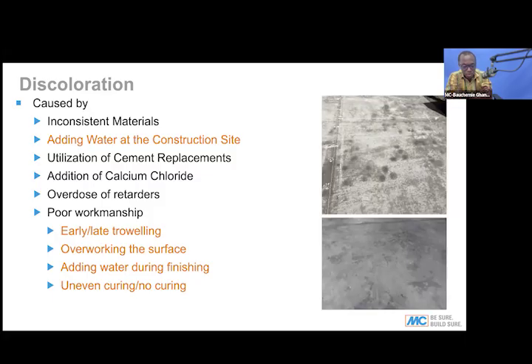Another aspect is when you are constructing, then you add so much water to the concrete. At the plastic stage, when the concrete is drying, you have water on the surface. When the concrete is drying, there will be moisture loss. The moisture loss will leave a lot of cement laitance on the surfaces. And on some of the concrete, when we are finishing, like the tool finish, and you finish on such laitance, you end up having some patches on the surface. You can see the picture on the screen, which has some black spots. All these are patches on the concrete when we are finishing it.